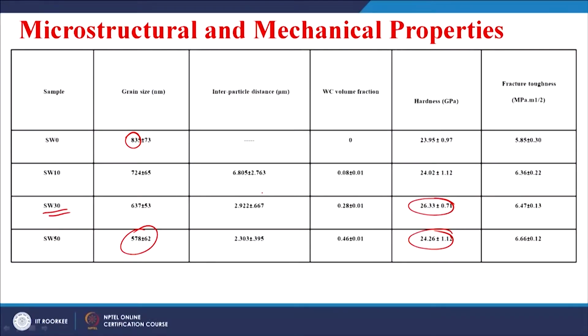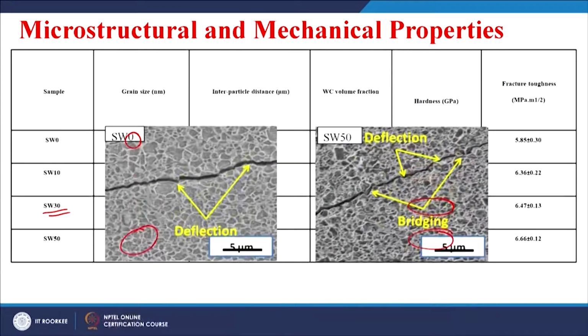content. So, it actually reflected in the properties, particularly hardness showed an increase for the silicon carbide 30% tungsten carbide composite, and the fracture toughness continuously increased from 5.85 to 6.66 MPa root meter. So, this fracture toughness improvement is very important for any structural applications. So, it is to be studied.